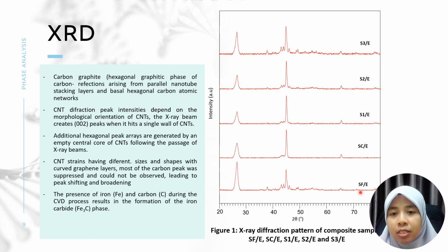So we have labeled it as SF, SC, S1, S2, and S3. So S1, S2, and S3 is actually by having mixture of different iron oxide and cobalt ferrite percentage as the catalyst to grow carbon nanotubes. For example, S1 is actually 20% of iron oxide mixed with 80% of cobalt ferrite, and then we use the mixture as a catalyst to grow carbon nanotubes. So S2 is 50% iron oxide mixed with 50% cobalt ferrite and use it as catalyst to grow carbon nanotubes. And the S3 is 80% of the iron oxide mixed with 20% of cobalt ferrite used as catalyst to grow carbon nanotubes.